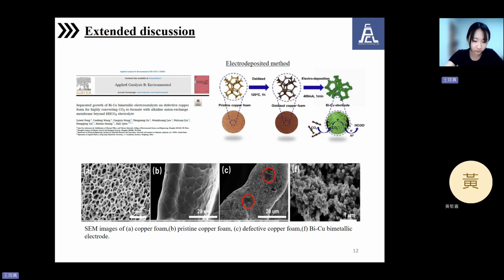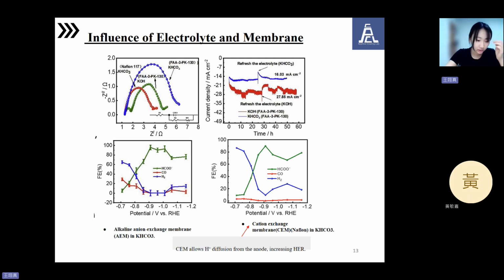However, it's important to note that the focus of this paper isn't just on the material synthesis. The authors mainly explore how different electrolytes and membranes influence the performance of CO2R. Let's look at this slide. In the EIS plot at the top left, we can clearly see that using KOH as the electrolyte leads to much lower charge transfer resistance than KHCO3, which means faster reaction kinetics and better electrical conductivity.